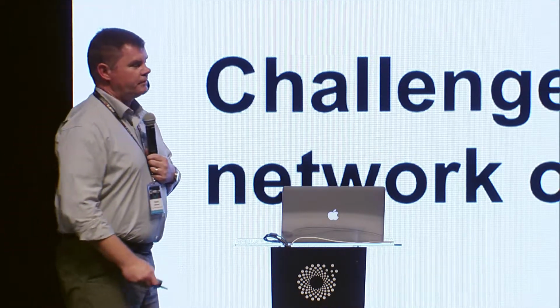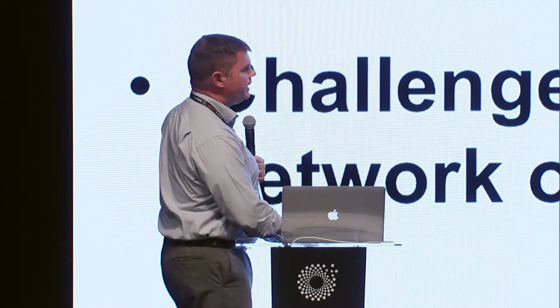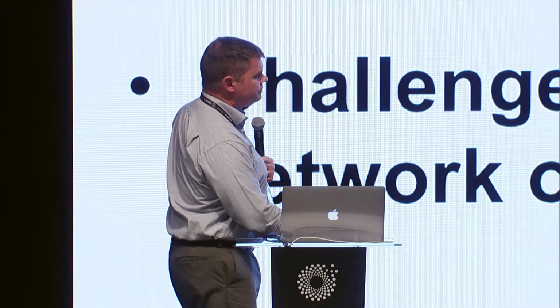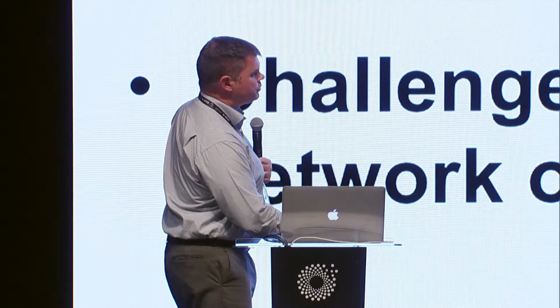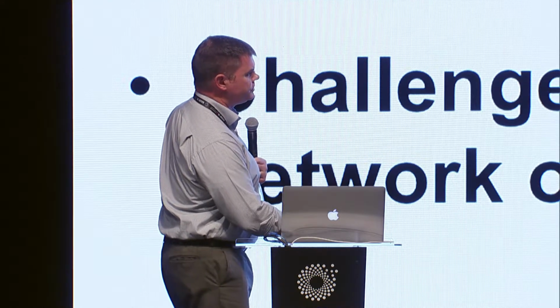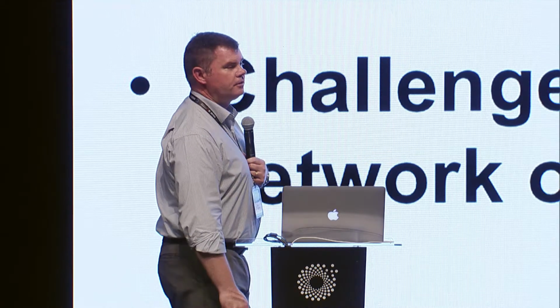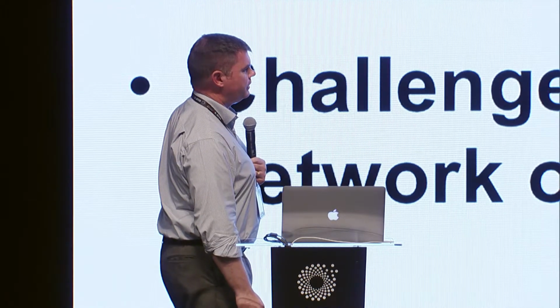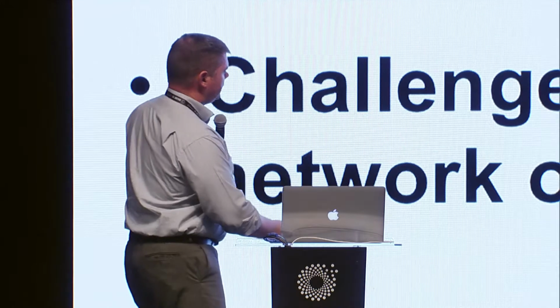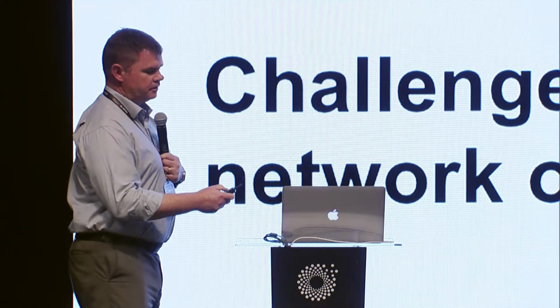Right? And that's significant. That's a key feature because when we've done that, we can increase both the intrinsic conductivity of the material as well as lower the percolation threshold that's necessary to make a conductive carbon network through the cathode. And so that's a key challenge for us into the future.